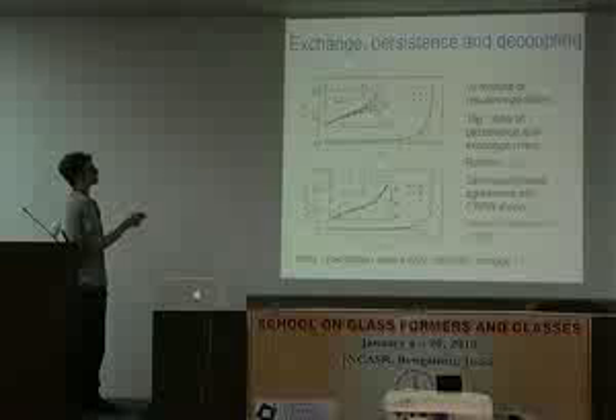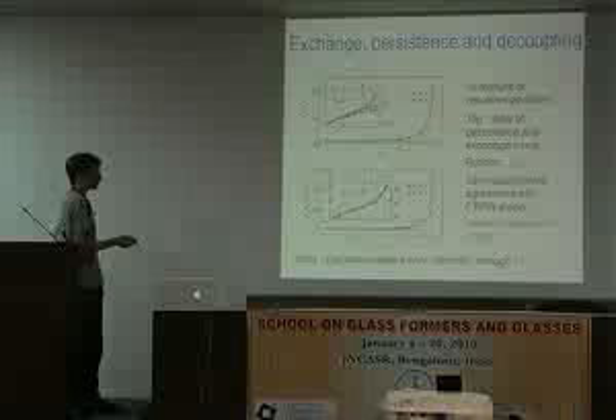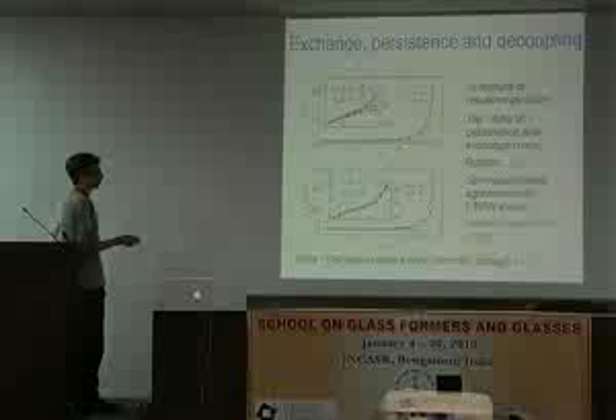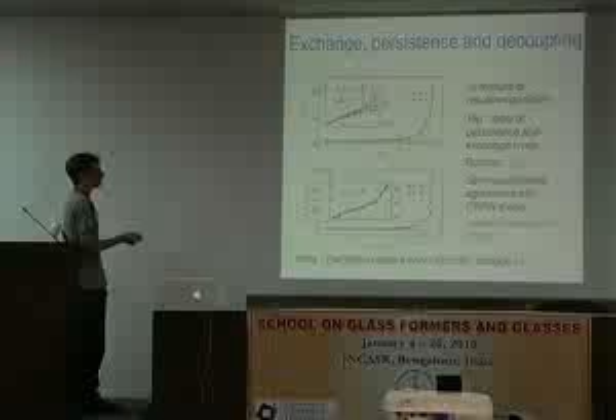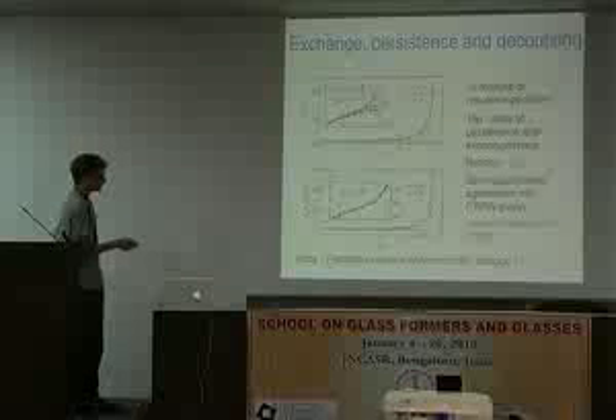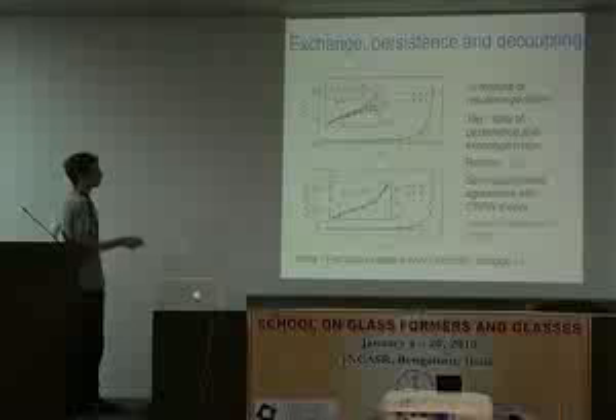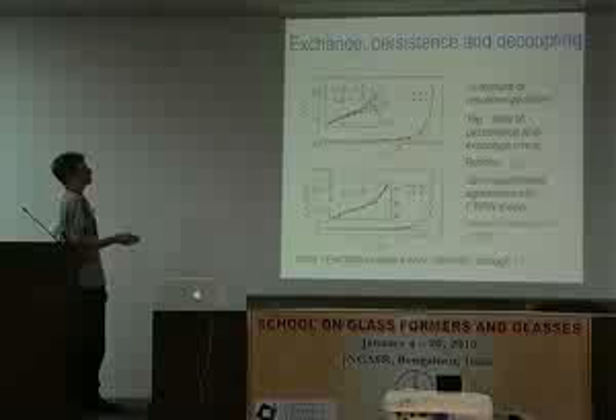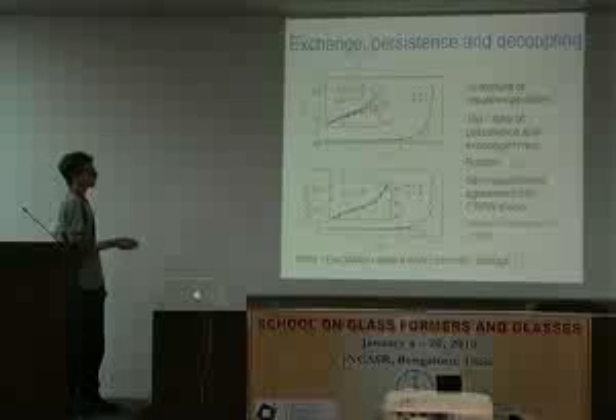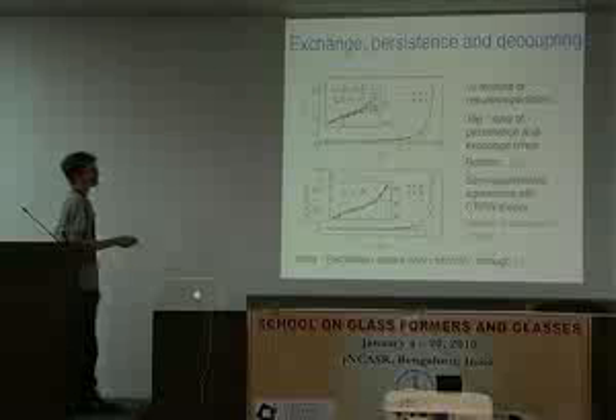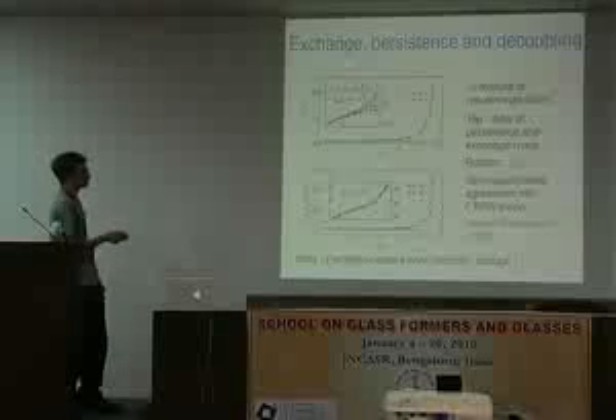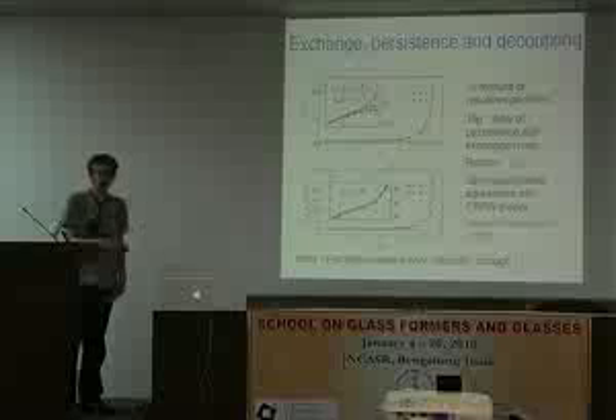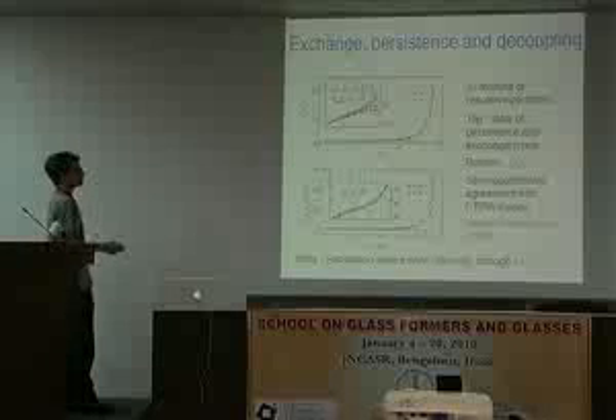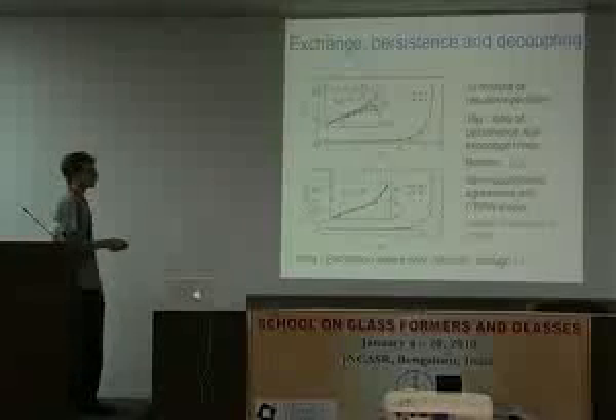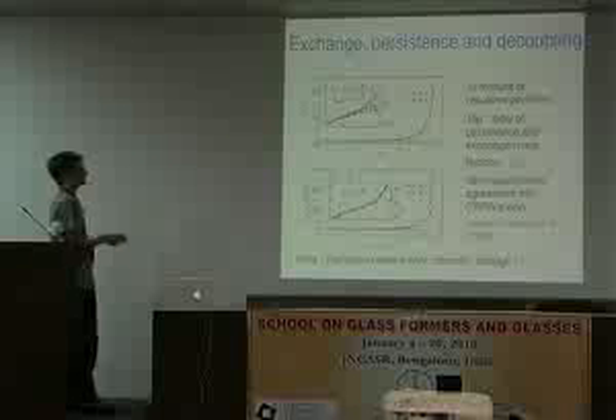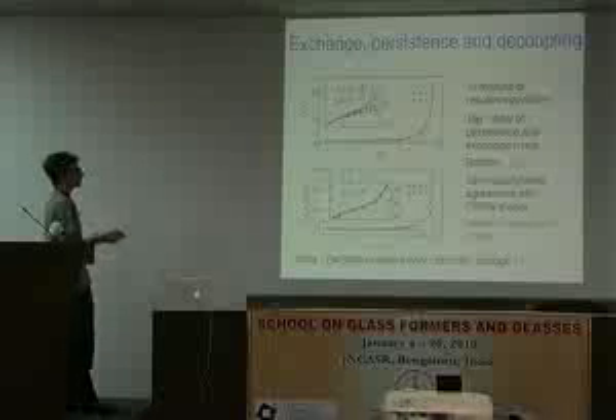Okay, so this is the ratio of persistence to exchange. And then this is the ratio of, or the product of the diffusion constant and the alpha relaxation time. This is just killing the units off. And you can see that, so there's two kinds of particles, it's a mixture. But you can see that the shapes of the curves look pretty good. The points at which they take off look pretty good. I don't know what happens if you take this data and try and put it exactly on top of that data. It's not the same. But it's pretty good agreement. So this is data. You can have issues with the data, but it looks reasonable.